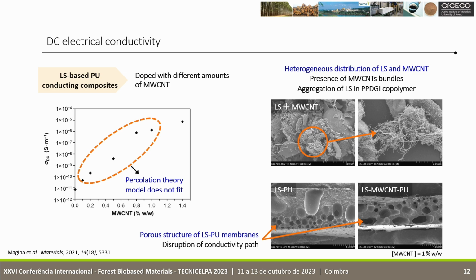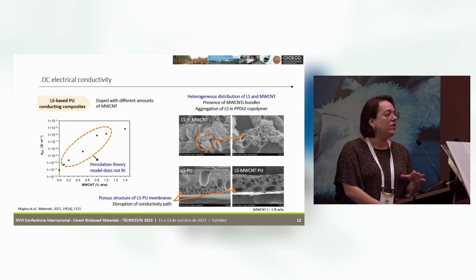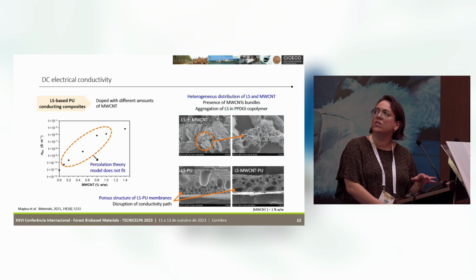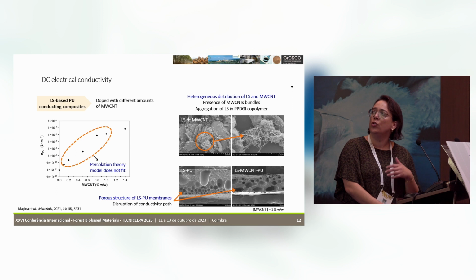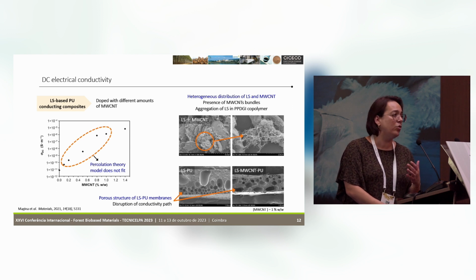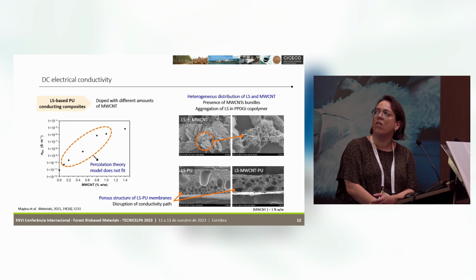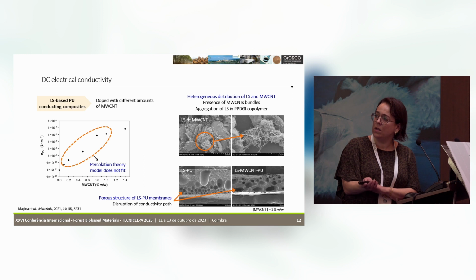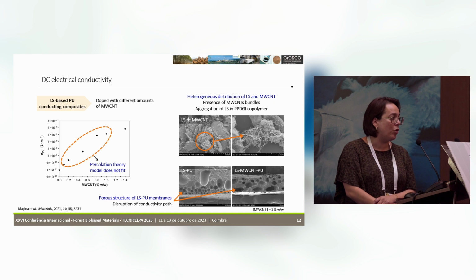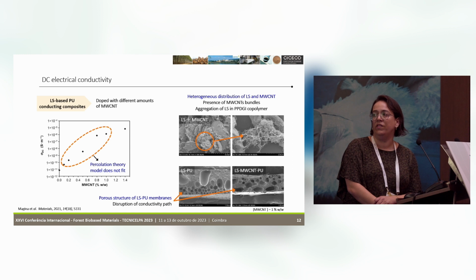...it doesn't fit the percolation theory model, which is expected for this kind of product, most probably because there were some difficulties in mixing lignosulfonates with the carbon nanotubes due to the presence of carbon nanotube bundles and also aggregation of lignosulfonates. Also, from the pictures of the membranes of the composite, you can see there are some bubbles trapped within, and this can also cause disruption of the electrical conductivity path.